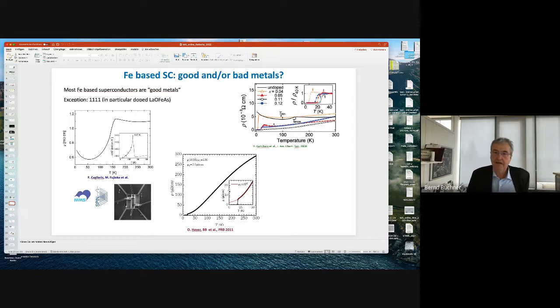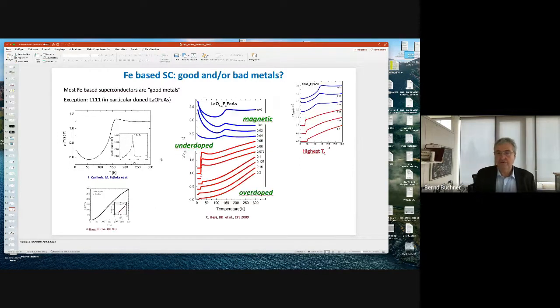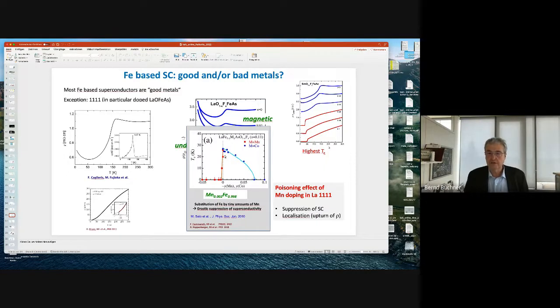And that's different in the others, these intermetallic compounds. So this is a resistivity for lanthanum iron arsenide, which looks like a beautiful, beautiful metal. This is a special situation that you have these oxides in between, and that and the coupling probably is stronger. And that therefore leads to the fact that we are really dealing with bad metals. And you have really to dope these systems to make it good metals and have it becoming superconducting. And still, these are the materials where we have the highest TC, do not forget. So these are the systems which probably show the strongest interactions. And in order to highlight that they are really strange metals, even if you take a good superconductor, plug in a tiny amount of impurities, superconductivity breaks down. It's really a very, very unusual material.